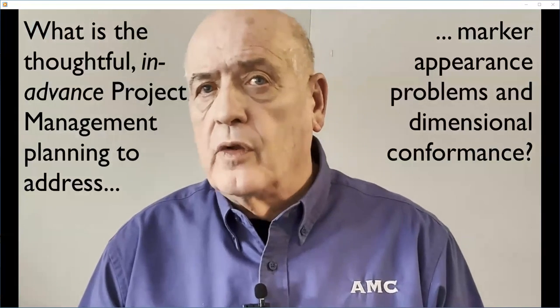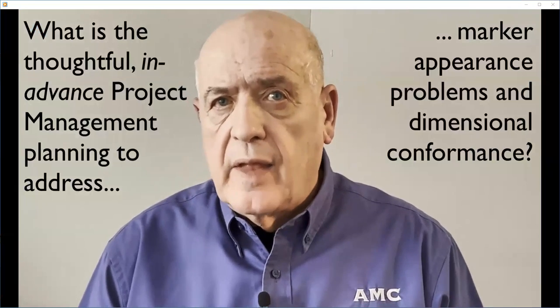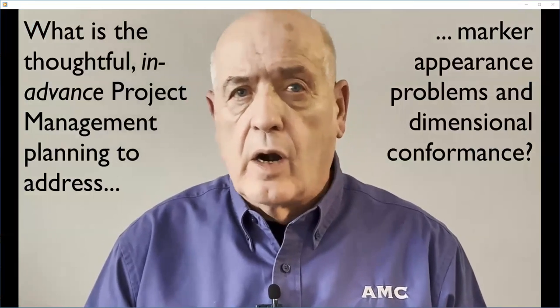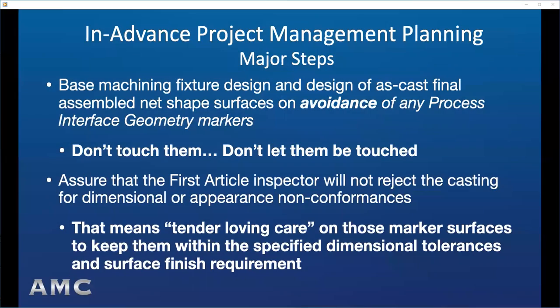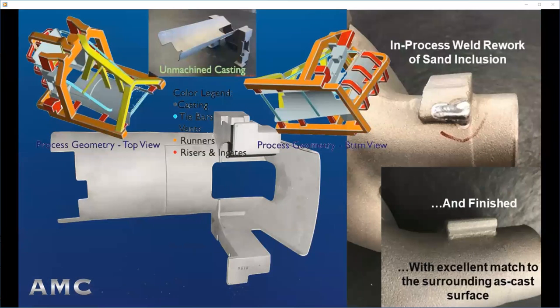So, what is the thoughtful, in-advance project management planning that can address all of these process interface geometry marker appearance and dimensional problems? Well, first, assuring that the upgrading of some as-cast surfaces to finished machine surfaces will be dimensionally conforming and consistent from casting to casting based on machining fixture design that avoids the markers. And second, assuring that the first article inspector, who is probably completely or mostly unaware of the presence and reasons for these markers, will not reject the casting for dimensional or appearance nonconformances. That means doing so essentially perfectly within the dimensional tolerance and surface finish specifications of the surrounding as-cast surfaces.